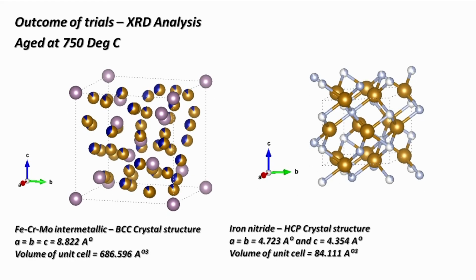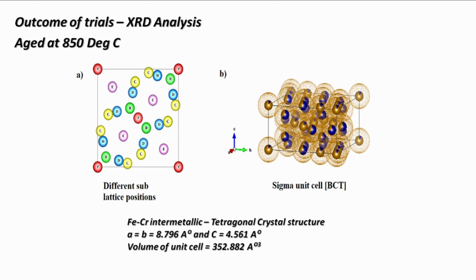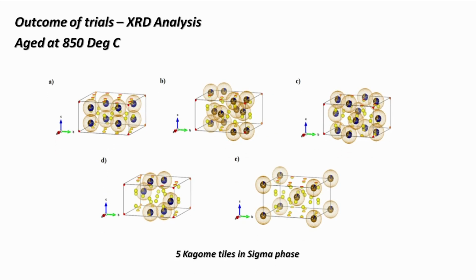And you can see iron chrome moly intermetallic, which is BCC crystal structure, which is chi phase, and some iron nitrides are forming around 750 degrees Celsius. And at 850 degrees Celsius, the secondary phase formed is a tetragonal crystal structure, which is sigma phase. So these are the sublattice points of sigma phase.